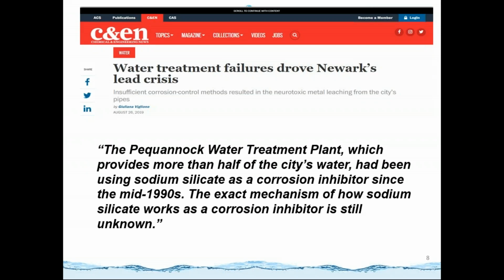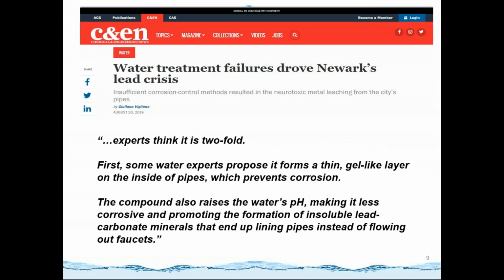In recent years, we can see some news about failures of distribution systems using sodium silicate. For example, in Newark, New Jersey, the local water utility used sodium silicate as a corrosion inhibitor to mitigate lead release from the mid-1990s. But even after decades of use, the exact mechanism of sodium silicate is still unknown. The water experts think there are two possible mechanisms. The first is that sodium silicate can form a thin gel-like layer, a protective coating on the surface of the lead pipe, which can prevent lead release.